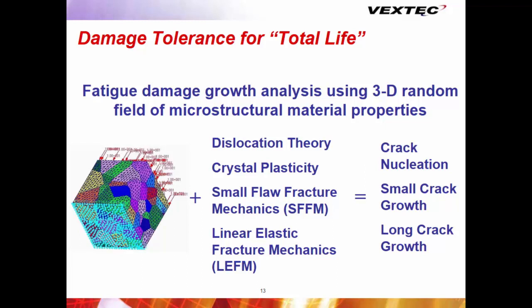The mean grain size is the same. The scatter in grain size is the same, as long as I'm in the same region. If I get to another region, especially in a casting, I might want to change up the statistics in my statistical volume element. But that element's available as an element, and then I've got crystal plasticity and dislocation theory models that allow me to generate plasticity through a dislocation. I was going to say Bilby-type models, Tanaka and Mura, the stuff that Keith Miller worked on for many, many years. There's many models out there.